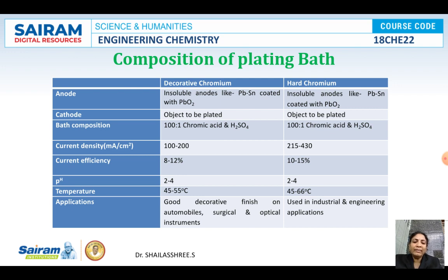The current density required, important, please do remember: for decorative chromium we supply 100 to 200 milliamperes per square centimeter, and in the case of hard chromium we need to supply 215 to 430 milliamperes per square centimeter. The current efficiency in the baths is 8 to 12% for decorative chromium and 10 to 15% for hard chromium, and the required pH in both cases is around 2 to 4. Acidic pH conditions are required, and the temperature for these processes is 45 to 55 for decorative chromium, and slightly more, 45 to 66, for hard chromium.